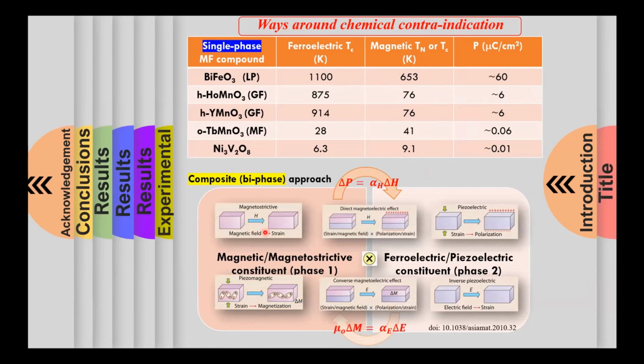In such biphase multiferroic composites, the magnetoelectric coupling is strain mediated. Now, what do we mean by that? When we apply a magnetic field, the magnetic phase undergoes magnetostriction. And this strain in the magnetic constituent is then transferred onto the ferroelectric constituent. And this strain in the ferroelectric phase generates voltage or polarization through the piezoelectric effect. So this is basically the direct magnetoelectric effect, where the magnetic field induces polarization.